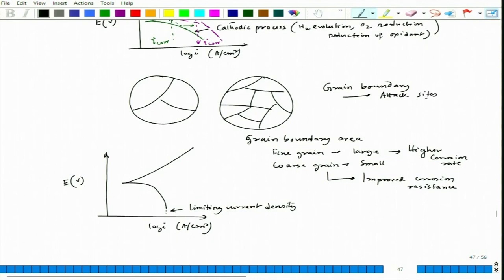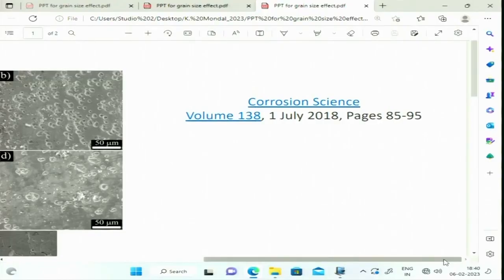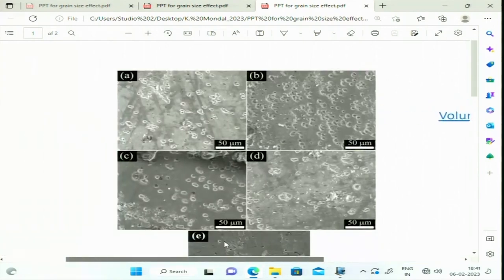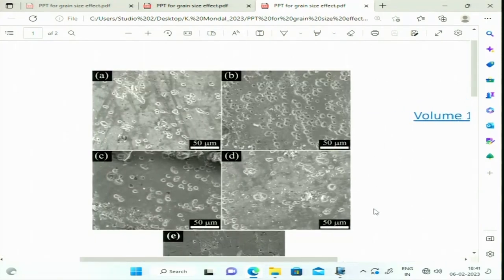Let us see whether we have some proof for it. For that, I would like to show you one particular result from a literature. So the literature is this one. In fact, this is one of our works. What we have done is we have tried to create a different grain size in a single composition steel. So that means composition is fixed, but the grain size is changed.